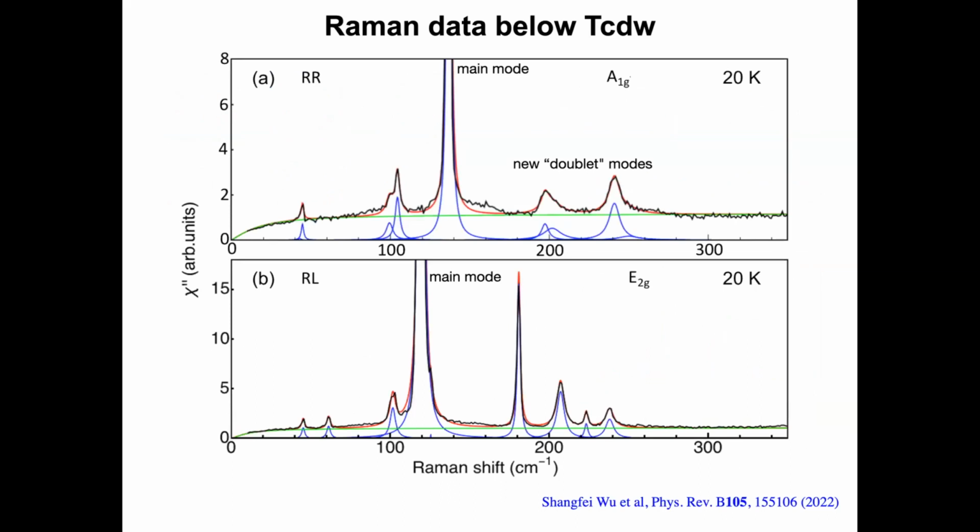Now, below the transition, there are fully symmetric modes, and those are folded modes, and you can see these which look like doublets. I didn't get confirmation from Leonard, I sent him an email, but I think what he was showing are these doublets. These doublets are fully symmetric. They are not really doublets. They are just folded modes. If you have a phonon branch which has little dispersion, after you fold it you will see 2 modes, and they are weakly separated. But this doesn't indicate broken C3 symmetry.